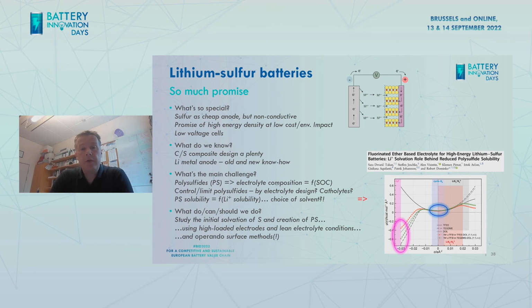So the main challenge here is very different to all the other chemistries I cover, because you're creating polysulfides from the sulfur host, and that means that your electrolyte composition will actually be a function of your state of charge. Of course, that is the case for other chemistries as well, but not at all to the same extent as for lithium-sulfur cells. So to control and limit the polysulfide solubility by the electrolyte design, for instance, or by using catholytes, which intrinsically have a lot of sulfur solubilized, that is really a key issue, a main challenge to be taken care of.